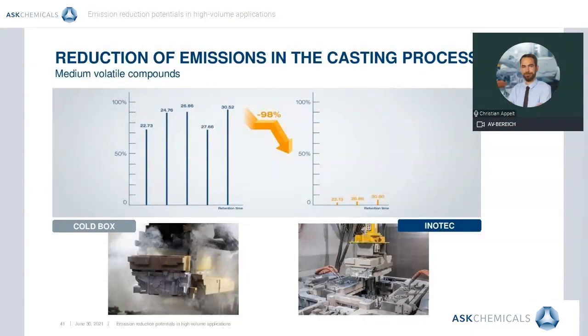The picture on the right shows the exact same casting process with a slight but important difference: the Inotec technology is used. In comparison, the formation of pyrolysis products from the binder system is completely absent. The Inotec binder system is only dehydrated and converted to a glassy state by the thermal strain of the casting process and remains inside the casted cores. A gas chromatographic analysis of the emission stream shows that 98% of the emissions can be reduced. The main improvement here results from the absence of medium volatile compounds, which are responsible for BTX emissions in the casting process using polyurethane standard cold box binders.